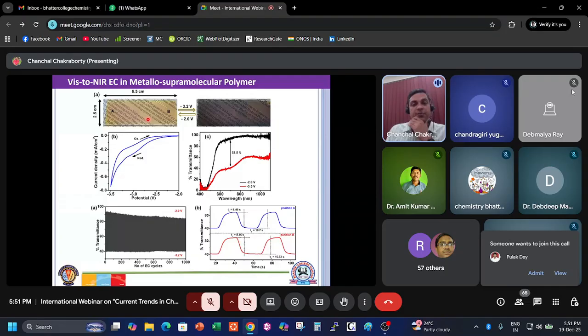We find that it can block around 70% of the solar radiation when you use the dark hue of this electrochromic device. And if it can cut down the solar irradiance by 70%, then the room temperature will be cool enough, as I told initially. To prove that concept, we designed a miniature home, a thermocol home. In that thermocol home, we installed our fabricated electrochromic device as the window, and through the window we irradiated IR light continuously and measured the inside temperature at different time intervals.